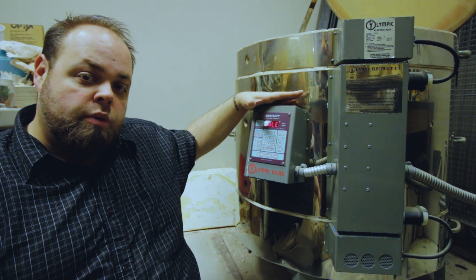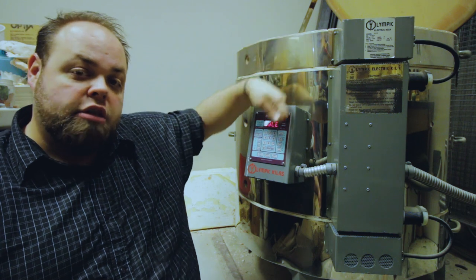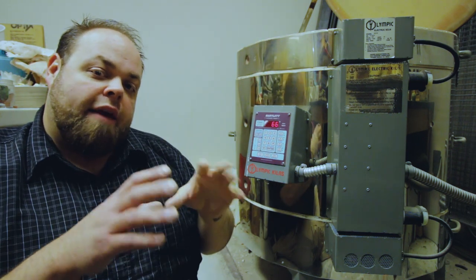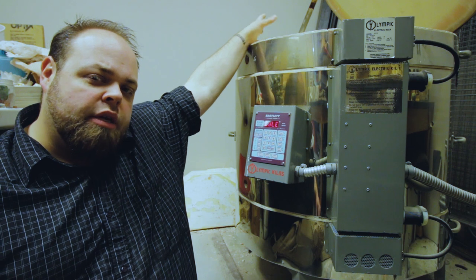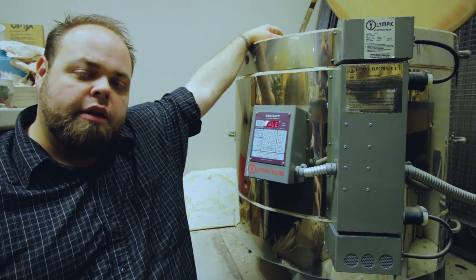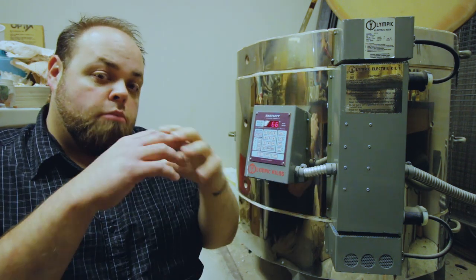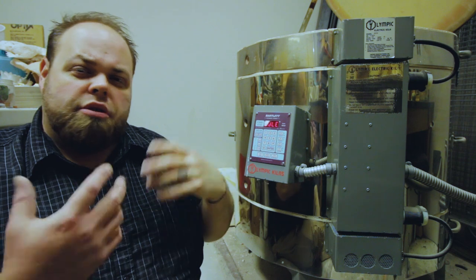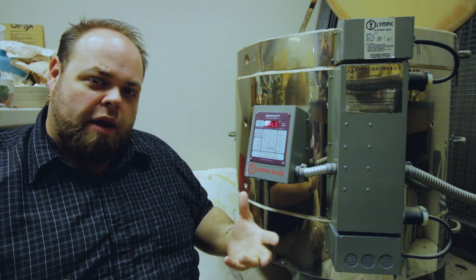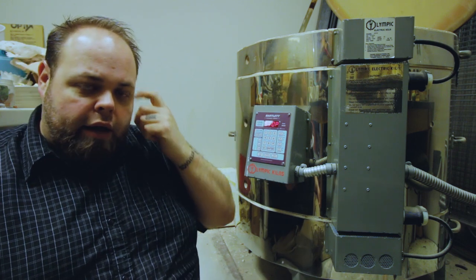For the full digital kiln, it will hold around 200°F during the preheat period. I recommend closing the lid on the digital kiln because mine goes directly from preheat into the firing itself. For a manual kiln you have to come back and change the knobs. What you're doing is getting that physical water to evaporate and escape. It's good to leave the lid open during candling if possible so that the moist air coming out of the clay doesn't get trapped in the kiln lid — that moisture wears down the lid over time.